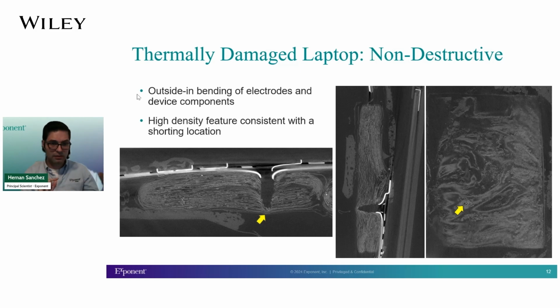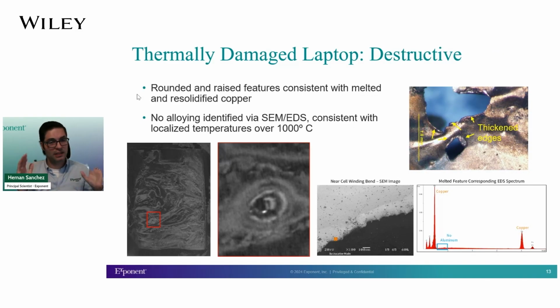And once again, if you remember the last example, that's the kind of thing that we're always looking for in this investigation. Is there something there that is telling us something that we should look at further? And that was the case: with that information, we were able to direct the destructive testing. In this case, we were able to find a location with raised and thickened edges, and it was just pure copper. Once again, the EDS proves very useful because now we know that this is a point that got over 1,000 Celsius, which is consistent, putting the story together, with some type of mechanical damage through the keyboard, puncturing the cell and causing a cell short at that location where we're seeing the end of that puncture.